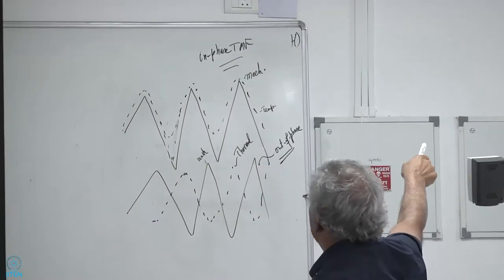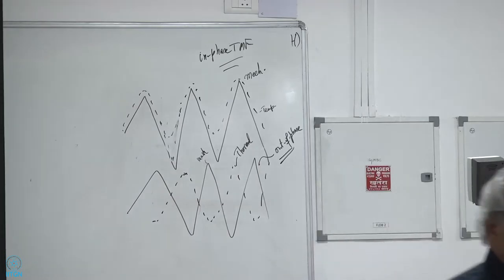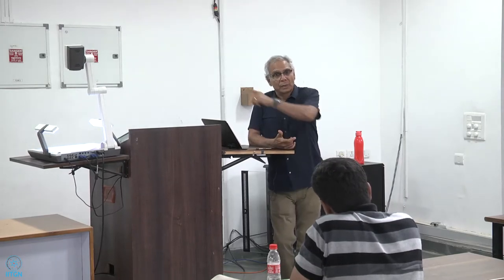No. You can only do that if you're doing it in a vacuum chamber. Because what did you do after all? All you did was you took a nickel-based superalloy and you welded it. It's still a superalloy. The only thing is the structure is a little bit cast structured. The welded structure is cast. It's not a wrought material anymore. And if you're now doing a fatigue test, you're exposing that to a high temperature, so oxidation will take place, and so will creep. Do you see what I'm saying? Yes. Okay. We can also talk about it a little bit more.